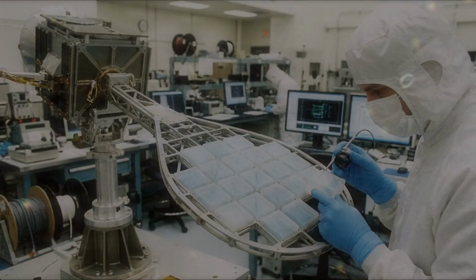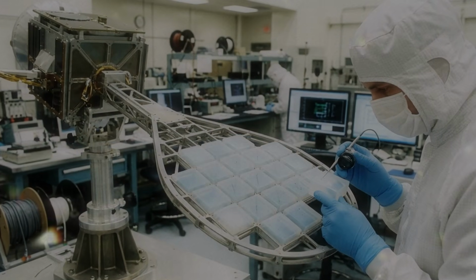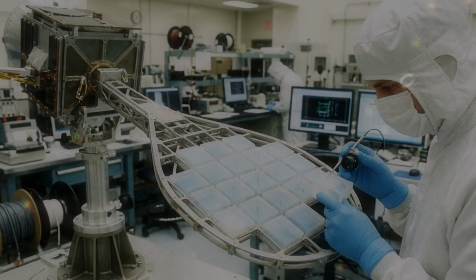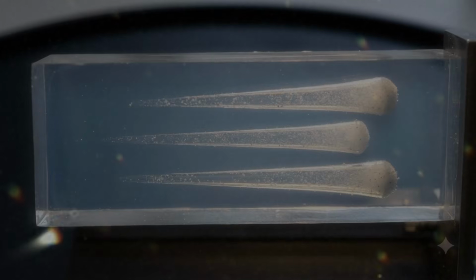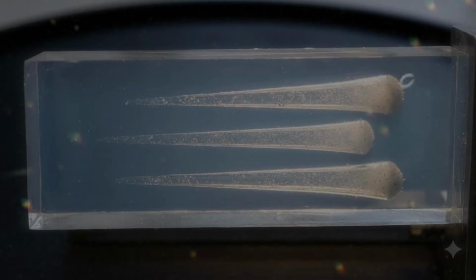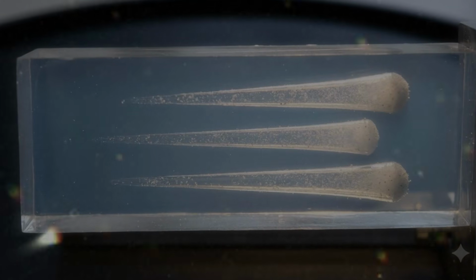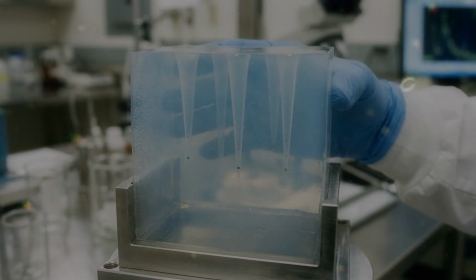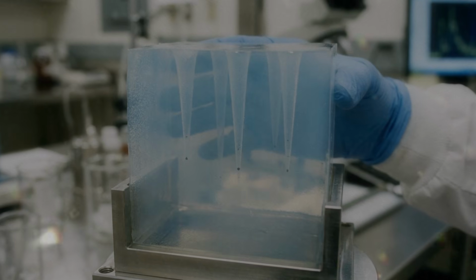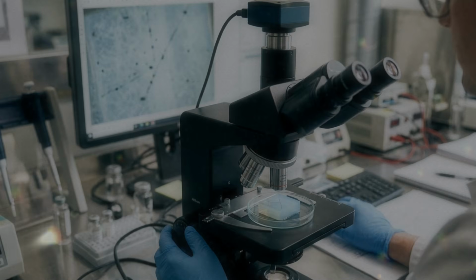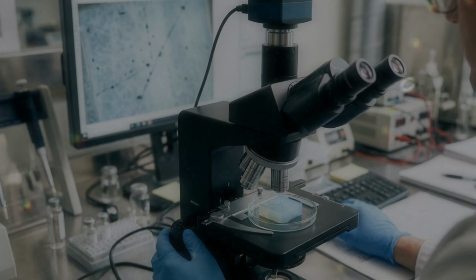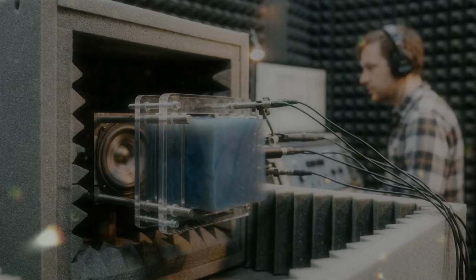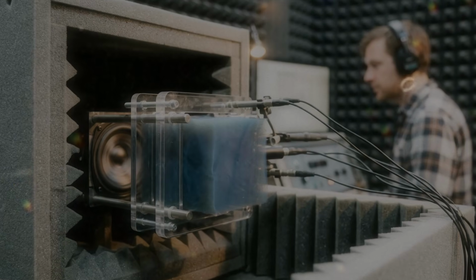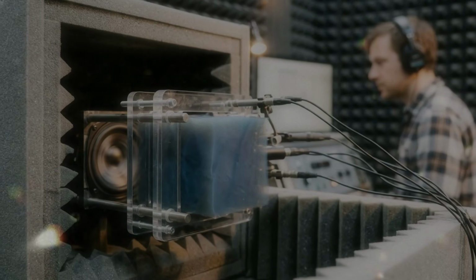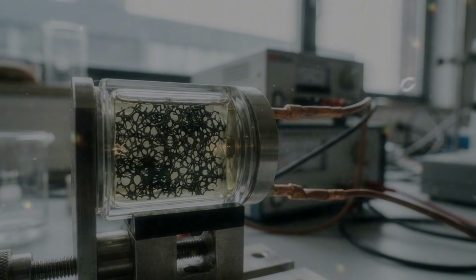Some aerogels are combined with fibers, layers, or cavities to improve performance. A dense skin may reflect part of the sound, while the porous interior absorbs another part. The result can be a material that provides thermal and acoustic insulation at the same time. This is attractive in aircraft, vehicles, buildings, and equipment where space and weight are limited. An ordinary wall may need one layer for heat, another for noise, another for fire resistance, and another for strength. A carefully designed aerogel composite could perform several of these functions within a thinner structure.